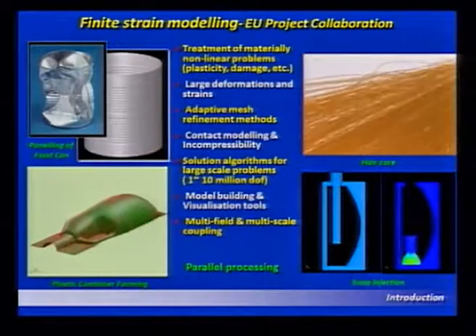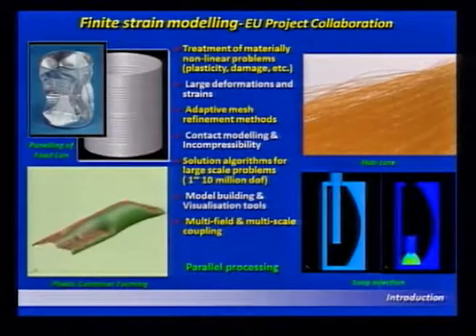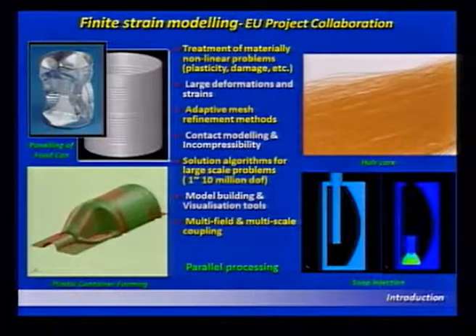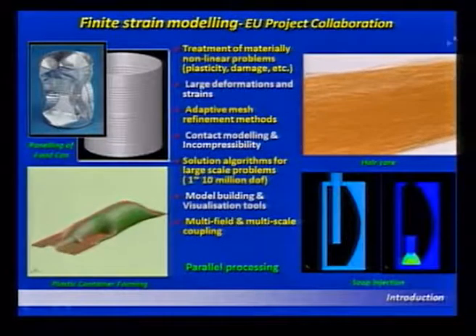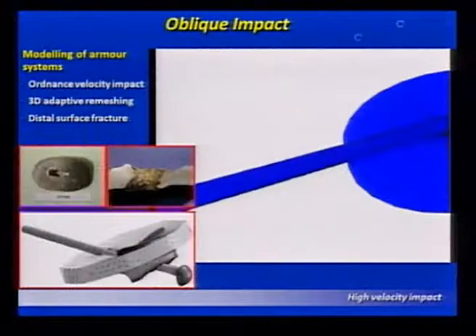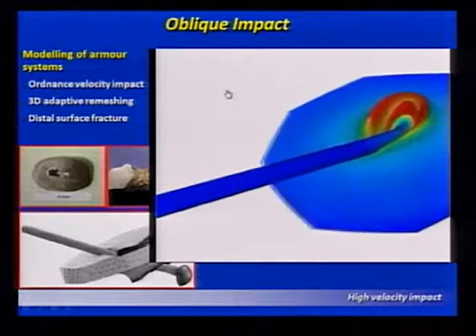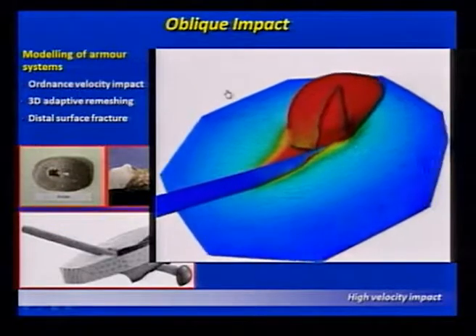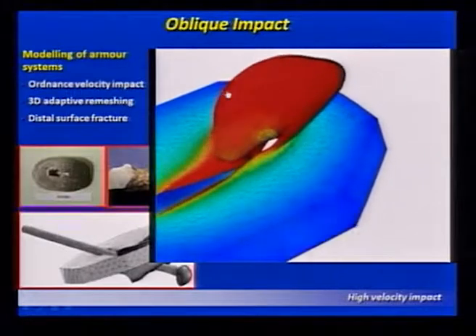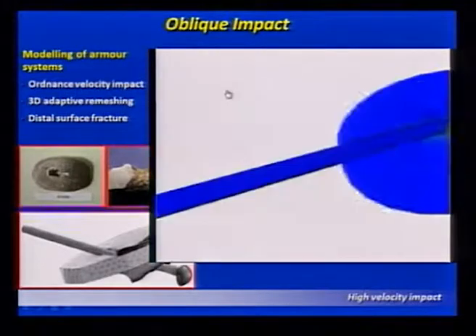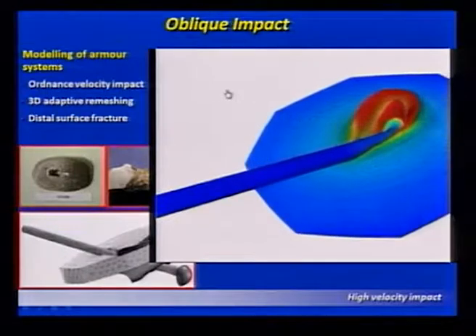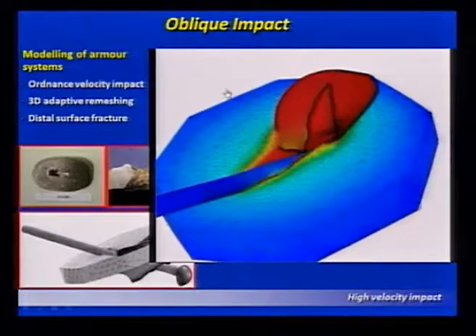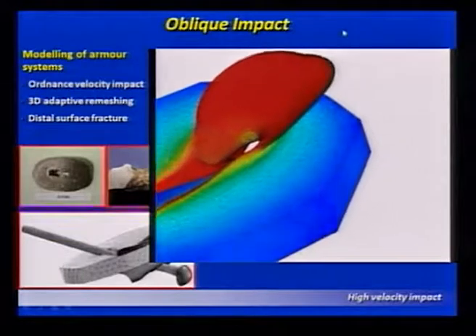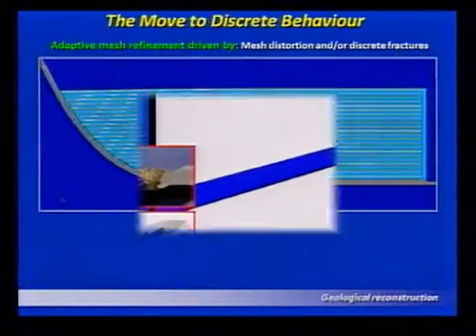And these kinds of problems, we worked together with UPC at that time. Lots of problems in the forming industry, and we were very successful. Another one is oblique impact. This is a case of a tungsten rod penetrating a steel plate, and you can see there's lots of large deformation there. There's fracture because the material has to penetrate the plate, and also mesh adaptivity plays a very important role. And this is the start of the move towards discrete behavior.